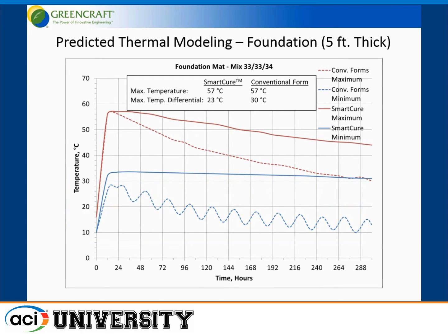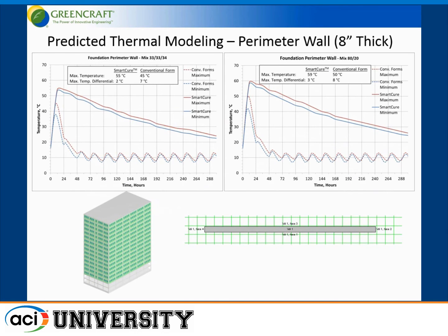We modeled the 1/3, 1/3, 1/3 mix, which would be a generally accepted mix for that application. The continuous line is the SmartCure concrete. The dotted line is a conventionally formed concrete. And on this mass concrete pour, you can see that we have less temperature differential between the core and the surface, while in the conventionally formed concrete, you're losing the heat a little more rapidly, but the biggest thing is you have the surface already losing heat at a higher rate than the core.